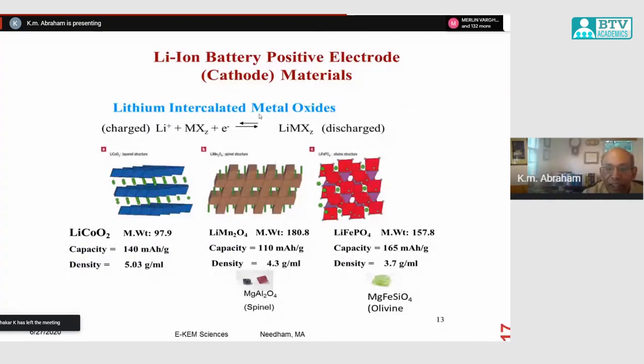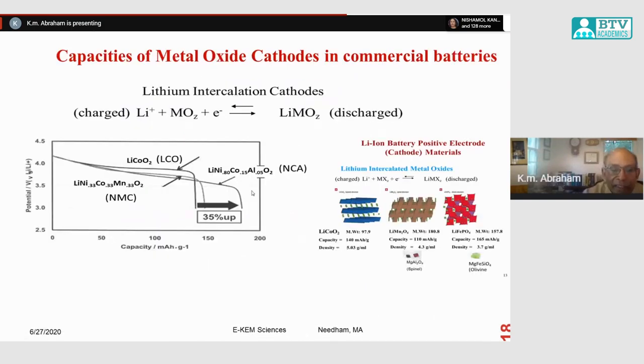So the intercalation electrode, as I said, the first intercalation electrode was cobalt oxide. Subsequently, people came out with other materials. Lithium manganese oxide is a three-dimensional material. You can see the lattice sites. These are open holes in the three-dimensional lattice, so the lithium can go in and out of that when you discharge and charge your battery. Another material is olivine, lithium iron phosphate. There are many others. So these are the materials that are now in commercial batteries.